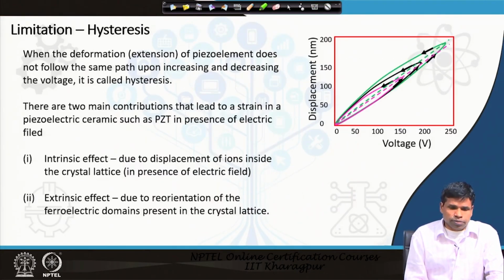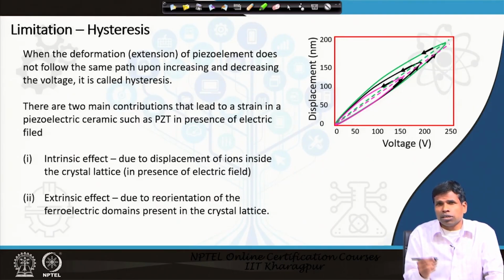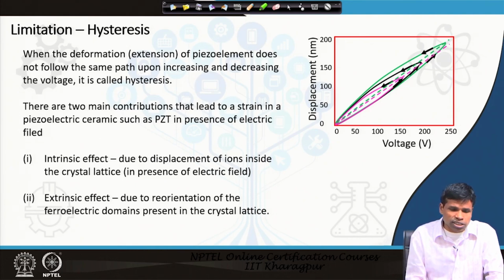Then another problem is hysteresis. Hysteresis occurs when we increase the potential, the displacement del z increases, and when we decrease the potential, it gets contracted, but they do not follow the same path. There are two main contributions that lead to the strain or displacement in the piezoelectric ceramic in the presence of an electric field, or on applying voltage. One is the intrinsic effect, which occurs due to displacement of ions inside the crystal, like in PZT we have the titanium atom, which is displaced upward from the center in the vertical position, as in the example I had given. That is the intrinsic effect.